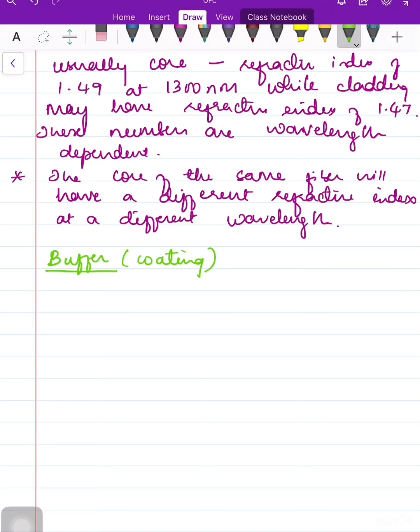A single microscopic nick in the cladding could cause the optical fiber to break when it is bent. So coating is essential for all glass fibers, and they are not sold without it. It may easily bend. The coating does not contribute to the light carrying ability of the optical fiber. It is not involved in the refraction which takes place in the core and cladding. It has nothing to do with the light carrying ability.